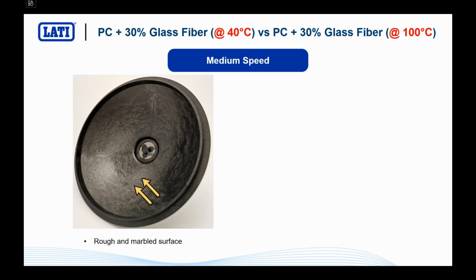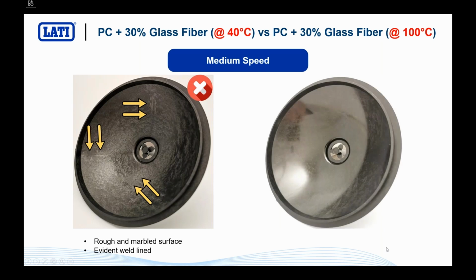For the picture on your left, 40 degrees C tool temperature, you still have a poor looking part, evident weld lines, very rough surface, totally not acceptable. But you can really appreciate an impressive improvement on the part molded with 100 degrees C. You put more energy in the tool and in the melt. And we will see what happened with high speed. You will see definitely improvement.